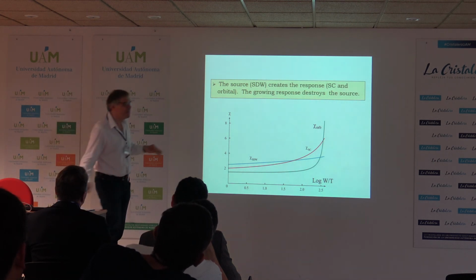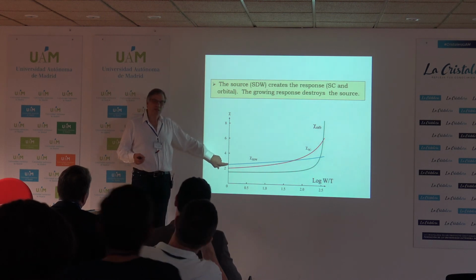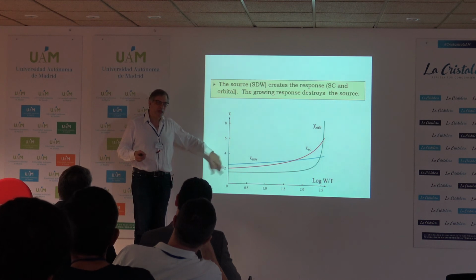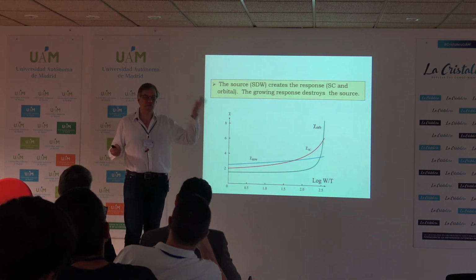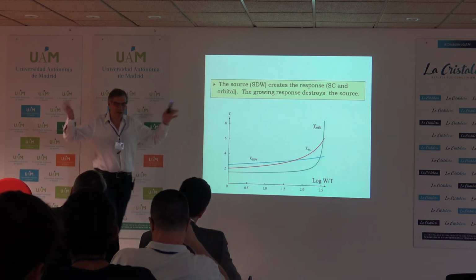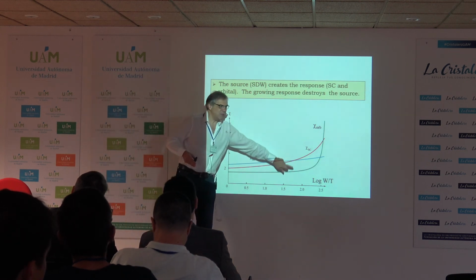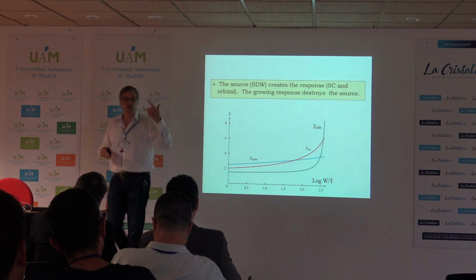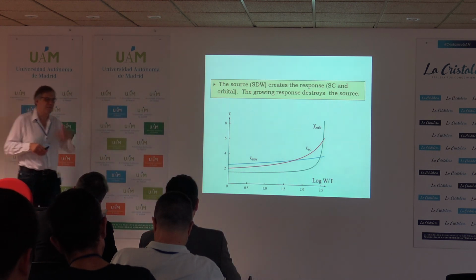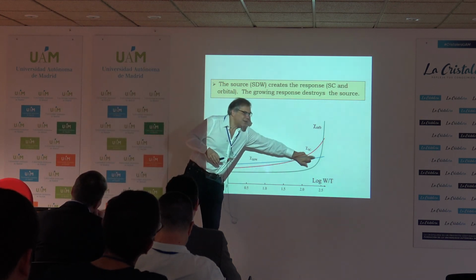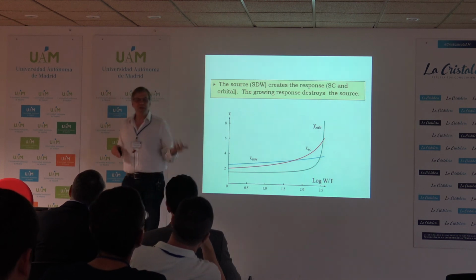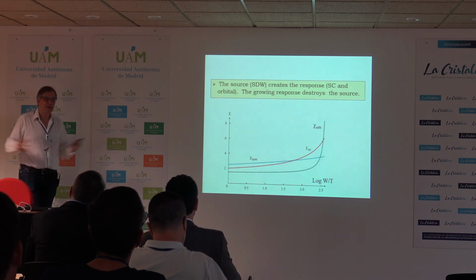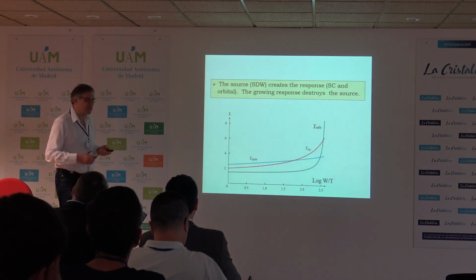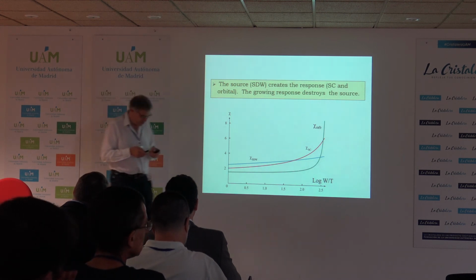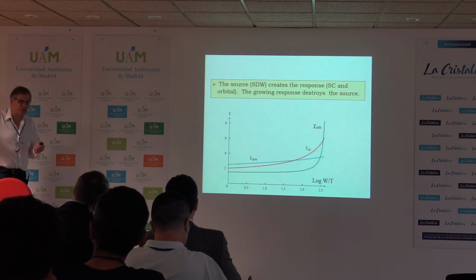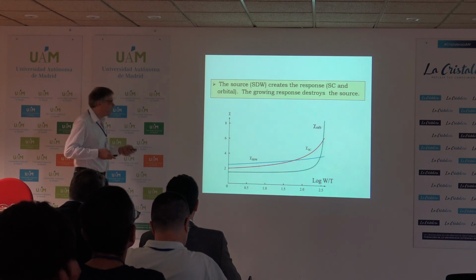So what does it mean? Why do we use the word political? Because read it this way. There is one interaction that was attractive, and the largest. It pushes other interactions from repulsion to attraction, right? So the big boss is promoting candidates. Then the candidates are promoted. They conspire to stop the growth of the channel that promoted the interaction in the first place. And this is exactly what happens here. At the end of the day, the magnetic susceptibility within RG does not diverge, because of the negative feedback effect from the 2 channels that become attractive. Their combined effect basically stops the growth of spin density wave susceptibility. And this is a nice example of RG when one channel promotes the attraction in the other channels, and then the other channels stop the growth in the channel that initially promoted everything.